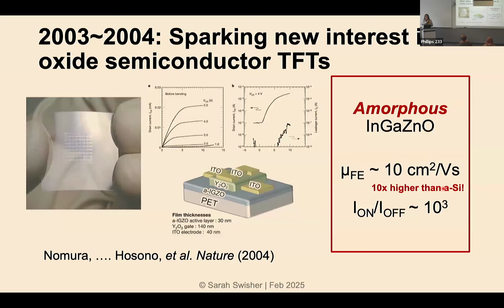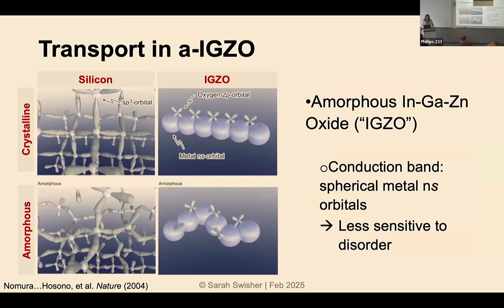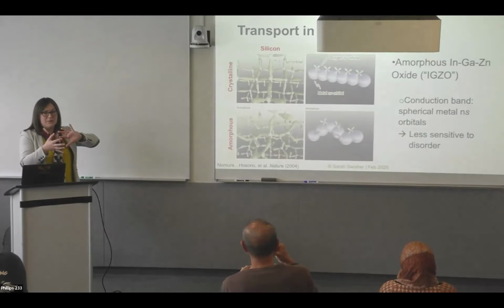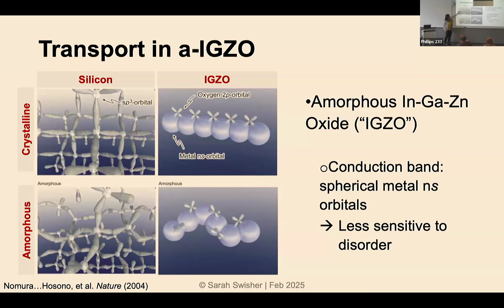And so the number of publications for IGZO and indium oxide-based materials since 2004 has been like a hockey stick curve. So the reason that these are so interesting from a materials perspective, and I won't go into a lot of detail here, is that if we think about a covalent semiconductor like crystalline silicon, we know that the transport is happening through these sp3 hybridized orbitals, and so bond orientation is really important. And if you have disorder in the system, you go from a picture that looks like this, where you have all this nice orbital overlap in your sp3 orbitals, to something like this, and your transport just tanks, right? This is why amorphous silicon is so terrible compared to crystalline silicon.